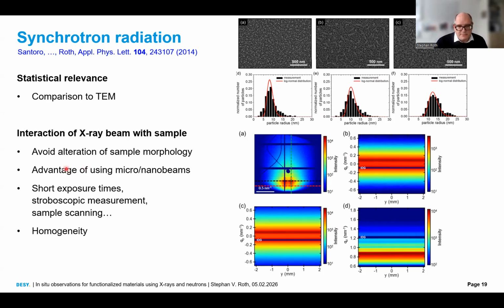And this is the advantage of using micro and nano beams. We avoid the alteration of sample morphology. We use short exposure times, stroboscopic measurements, and sample scanning, and at the same time you can check if the people who spin coated, in that case, the sample made a good job, and if the sample is homogeneous. So this has only advantages.